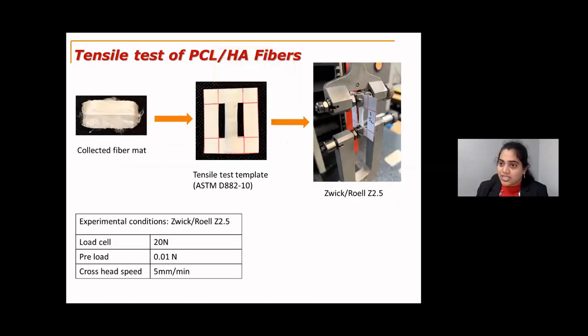Whether the tensile testing machine is indigenously developed or the setup is already available. This load cell was customized for low loads. For the Zwick Roell, earlier we used to have a 20 kilonewton load cell, but now we customized it to 20 newtons, so it can measure 0.001 newtons. We specifically asked this particular industry to develop this load cell to check the fibers. We check human hair, single filament fibers, and everything with this.